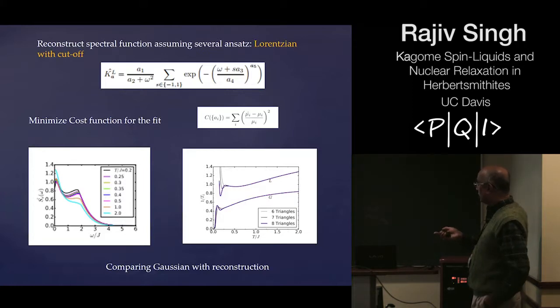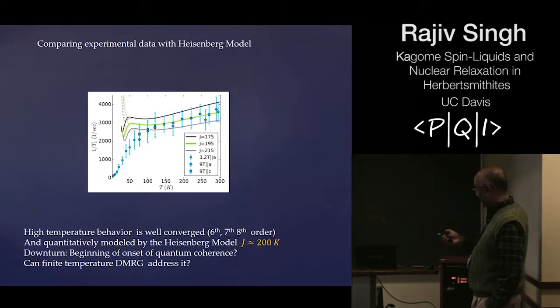By inverting this information we try to reconstruct the line shapes, and then basically our calculations break down at low temperature, but at high temperatures they represent the experimental data very well with no adjustable parameters really, because the hyperfine couplings are known, and the exchange constants are also known from other experiments or from first principles calculations. So that suggests that the Kagome system is still reasonably well described by just the Heisenberg model.